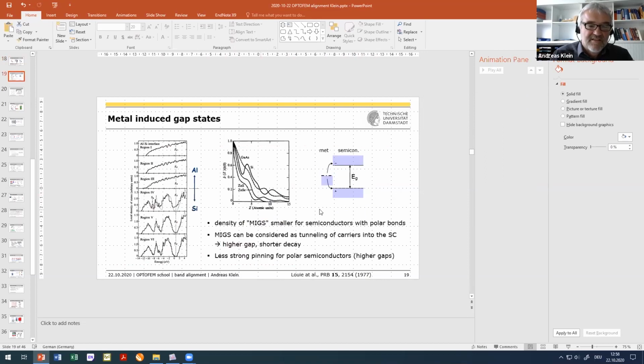This is the distance from the interface, and that's the density of the induced states. And you see that for silicon and gallium arsenide, they are decaying much slower. And they are decaying much slower because they have smaller band gaps. Because this tunneling barrier will increase when you increase the band gap, and that means it will decay faster. But that's a very qualitative argument.